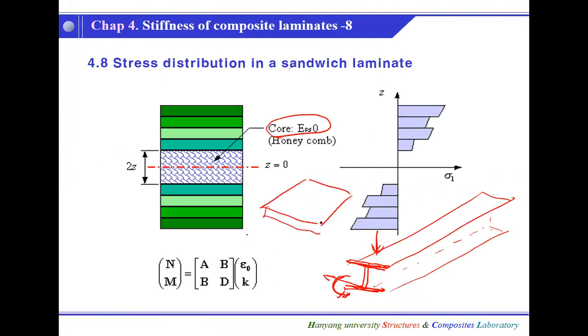Say we have a laminate. We have a certain load like that. And if we just stack this laminate like that, bending stiffness this way is very low. Very low. So the most effective way is to split it in half. This is the half and the other half. And then let's put what? Core inside. Okay. So compare the weight between those two structures, this one and that. Weight is almost the same.